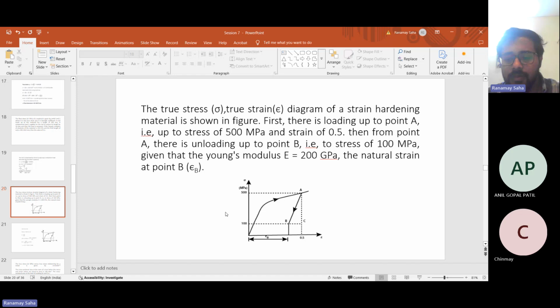Okay, so let's see the solution now. The problem deals with determining the true strain value after the material has recovered to some extent, undergoing some elastic recovery, but didn't come back to its initial position. You can solve it by simple geometrical concepts. If you simply drop a line from A to the abscissa, you know the strain at point A is 0.5. You also know the true stress values corresponding to point A and point B. Now, AC by BC is the slope of this line, the path that the material follows while coming back during the unloading process.